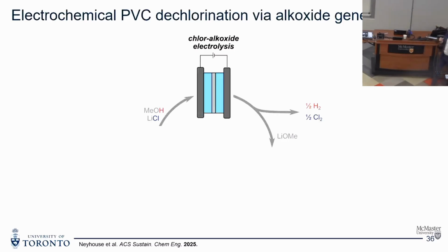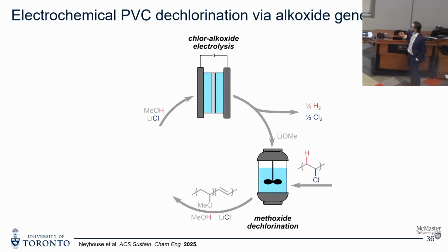So what we ended up doing as an overall process is we built this up, and we decided to separate our polymer deconstruction and our electrochemical steps. So we have what I'm calling chlor-alkoxide electrolysis, where here we're taking methanol and lithium chloride. We electrolyze that. We generate chlorine at the anode, hydrogen at the cathode via hydrogen evolution from methanol, and we generate a lithium methoxide base. Lithium methoxide is a really potent base for PVC reduction at very mild conditions. So we can take that base, feed it into a dechlorination reactor, react that with PVC. We liberate that lithium chloride, methanol, some dechlorinated PVC.